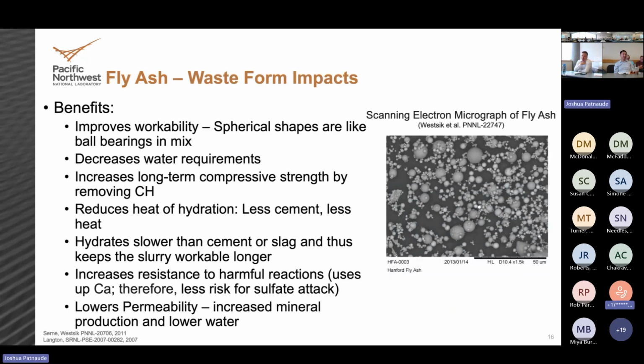So what do we use it for in terms of waste forms? One of the biggest uses for it is it improves workability. So it improves how, when we're mixing the dry reagents of the liquid waste and water, the fly ash really helps with the rheology of that resulting slurry and keeping it flowable and keeping it movable. The reason for that is pretty practical. The little fly ash beads that come out look like little tiny ball bearings or little balls. So physically in the mixture, if things are moving around, if you have sharp edges, they can physically run into each other, and that makes mixtures thicker. But these little balls of fly ash are in there, they're just rolling around in the slurry. So it really helps us be able to mix what would traditionally be a tougher mixture together. It decreases the amount of water we have to use. It produces less heat, so you have lower energy there. You can delay set times.